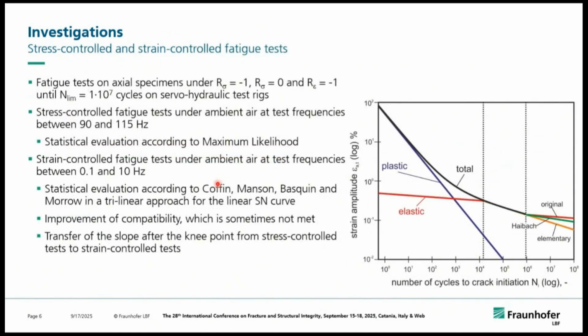Coming to the fatigue tests, we made stress and strain control fatigue tests, stress control tests up to 10 to the power 7 cycles for alternating and tensile loading to get information on the notch effect. We had test frequencies around 90 to 115 hertz and made the evaluation according to maximum likelihood. And in addition, we made the strain-controlled fatigue tests in the range up to 10 hertz.